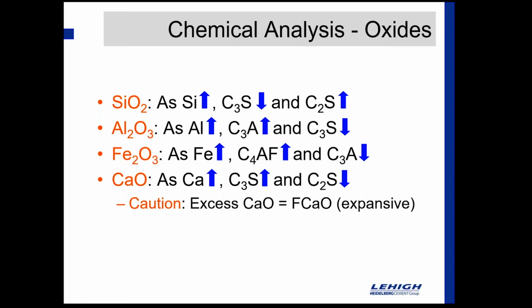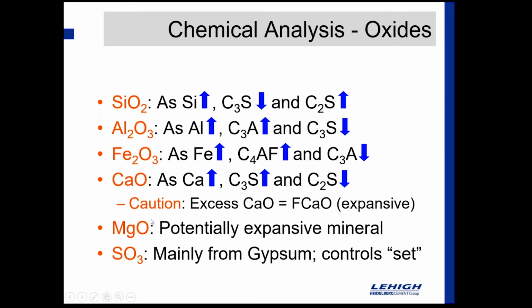And you can't do this without consequence, because if you have excess lime in the mix, that's called free lime, and that free lime becomes an expansive mineral. And then just a couple other oxides and their impact on the overall cement performance. Magnesium oxide, potentially an expansive mineral if that gets too high. And SO3, again, this mainly comes from the gypsum, and this is required to control set.